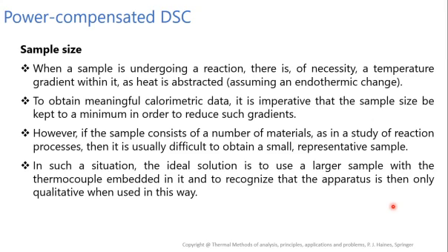Then what about the sample size? When a sample is undergoing a reaction, there is necessarily a temperature gradient within it. So, assuming that heat is absorbed, this is an endothermic change. To obtain meaningful calorimetric data, it is important that the sample size be kept to a minimum in order to reduce such gradients. Okay, so the sample size should be minimum.